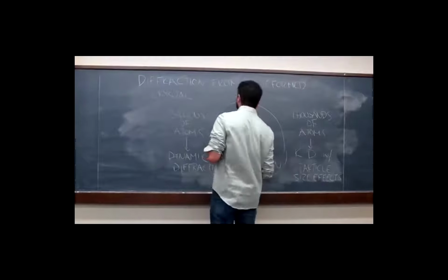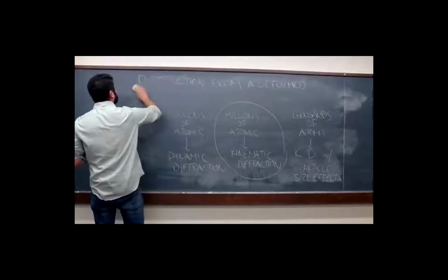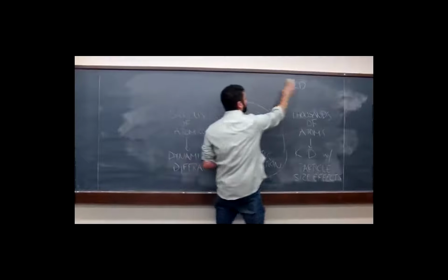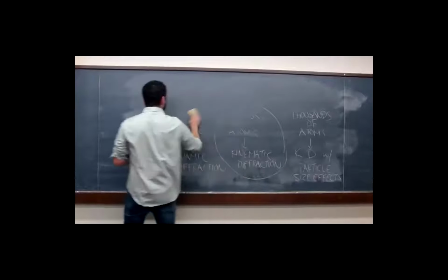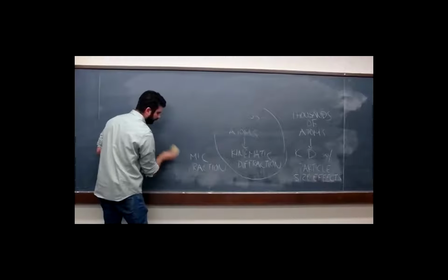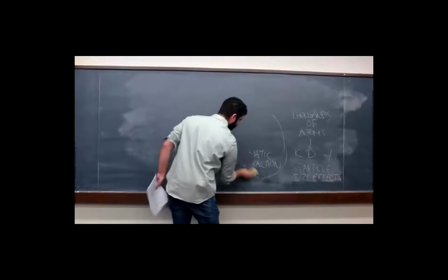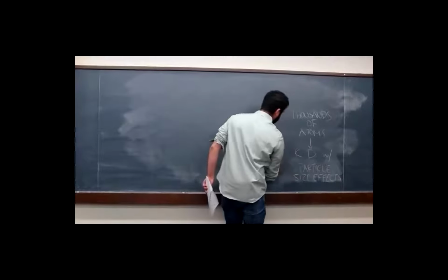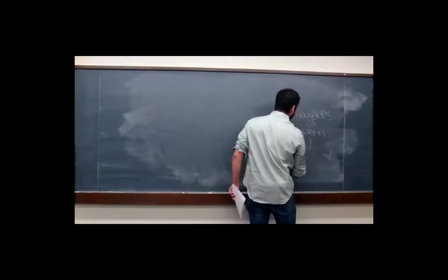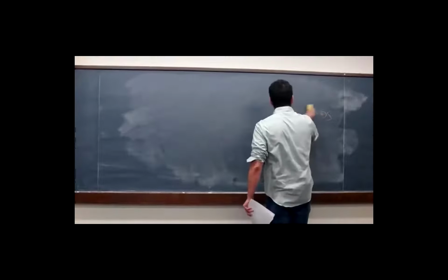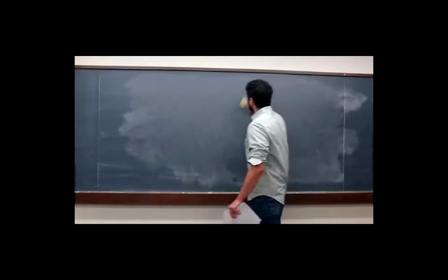In all the analysis that we did previously, when we were talking about our rotating crystal diffraction experiments, we assumed that the crystal that we were looking at, or crystallite, was on the center of rotation. If we're dealing with these real crystals built up from lots of little crystallites, there's no way that all the crystallites can be on the center of rotation. And the positions of these crystallites can end up influencing our diffraction data.